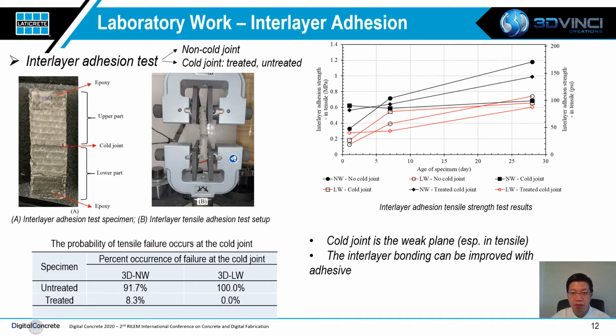In order to improve the grip between the specimens and the gripping plates, we applied epoxy at both tips of the specimens. The surfaces of this epoxy were also roughened to improve the grip when it is hooked to the testing apparatus. The test results indicate that the normal weight material has better interlayer adhesion than the lightweight. The bonding strength between the layers was also found to increase as the specimens age.